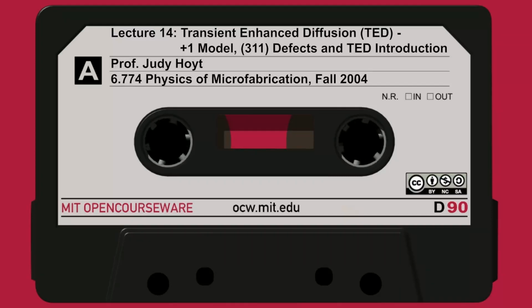Because if I'm going to say that boron's diffusivity depends on f_I times this ratio, and let's say I'm at 800 and I'm in a period where I have TED, well, at 800, C_I over C_I star can be as large as almost 10 to the 4th, maybe mid 10 to the 3rd. So it gives you an idea of the magnitude of the enhancement in the boron diffusivity. Relatively simple derivation, you can get an idea right off the bat of how much C_I over C_I star can be enhanced during the steady state period. Now, eventually it's going to end.